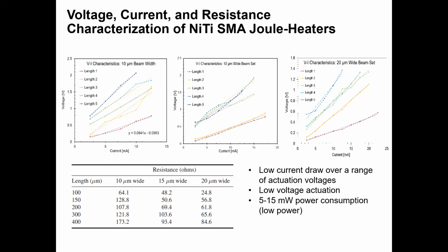The slopes of the IV curves were used to generate this table of resistance values, and it matched the expected trend. In other words, the widest beam with shortest length exhibited the least electrical resistance, in this case about 25 ohms. By comparison, the narrowest and longest beam exhibited the highest electrical resistance of 173 ohms.